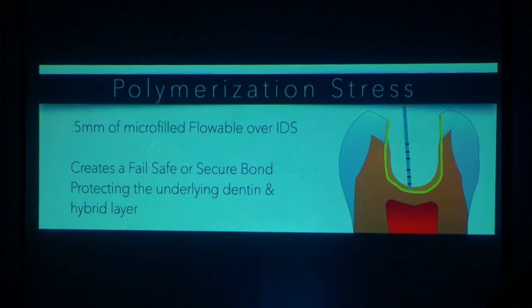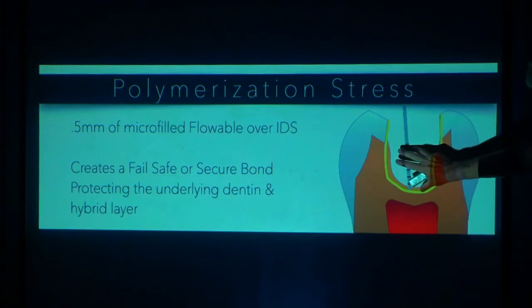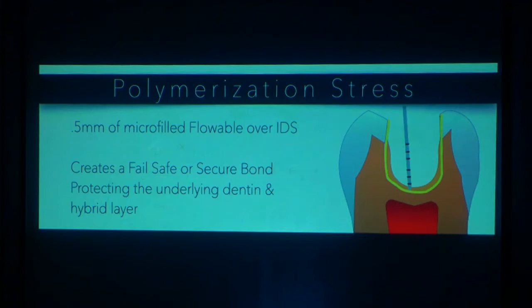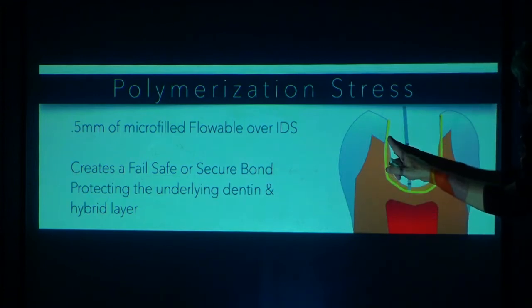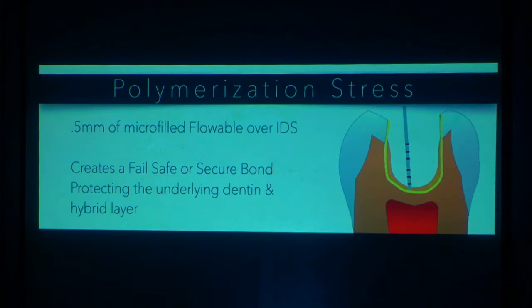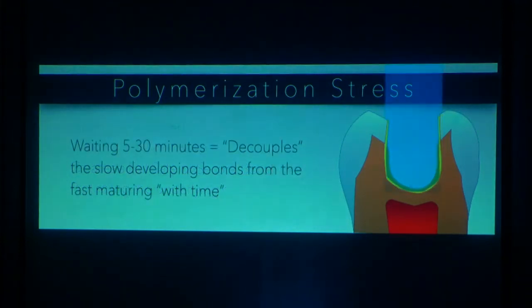Now again, if we do a layer of this resin coating at 0.5 and we compare that to the bonded surface here, what's the ratio? About the same. It's still a ratio of about one. So right now we've got a half millimeter of composite on the tooth. Just a half millimeter. All of that composite is moving towards the tooth. Plus, it takes time to do this. How long does it take to do a careful resin coating and a light cure polymerization? It takes a minute and 30 seconds. And so we're trying to wait for 5 minutes to have that polymerization curve get up to the plateau.